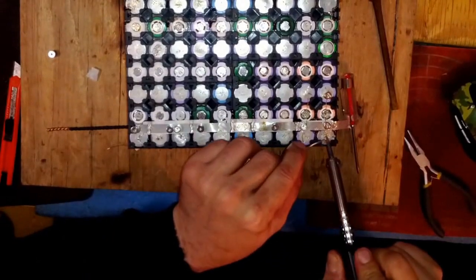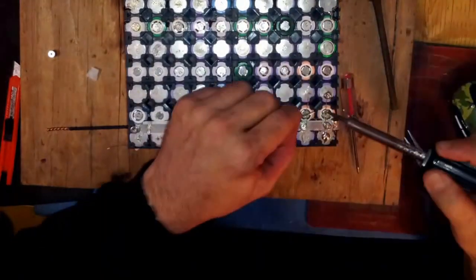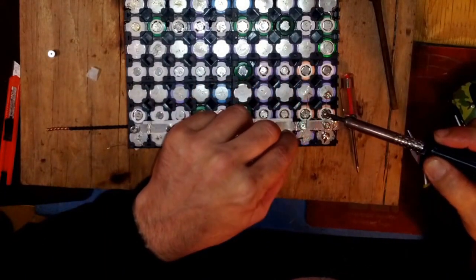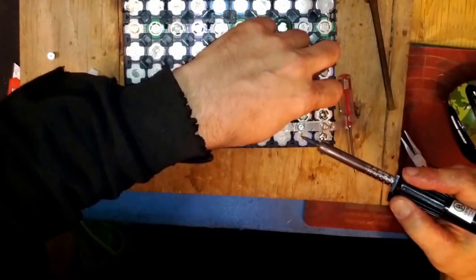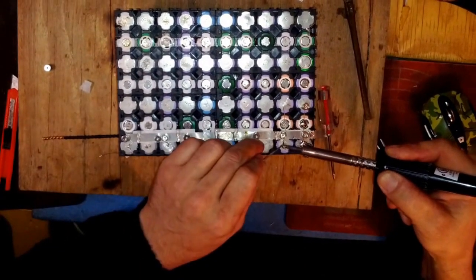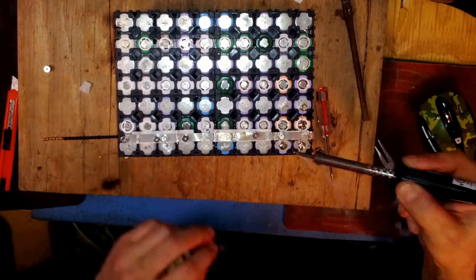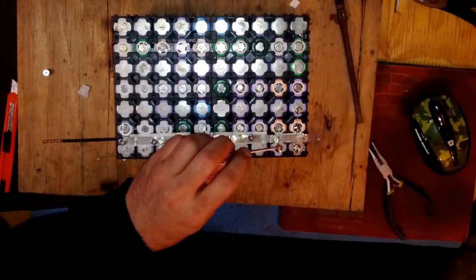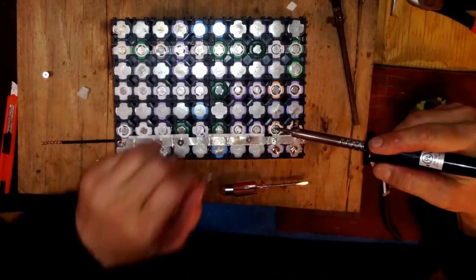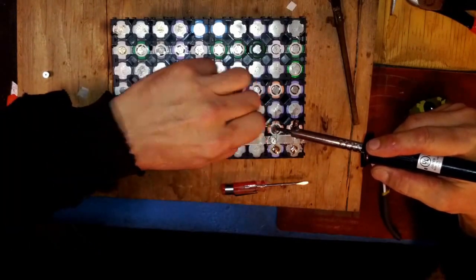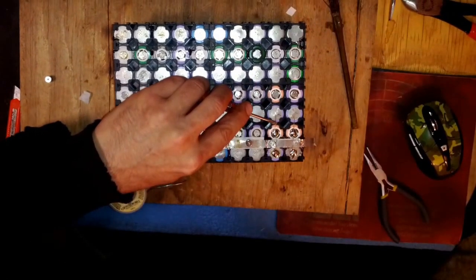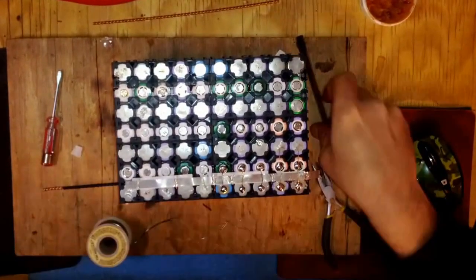While I would have liked to have had one of those solder flux pens, I didn't have one so I ended up using just regular flux paste. I put that on the cells and the nickel bus bar and that minimized the amount of contact that I needed with my 30 watt iron on the cells themselves. There are some good videos out there on YouTube about the effects of heat on the cells.